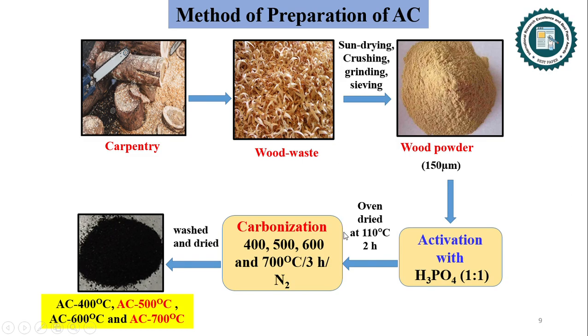The mixture was then heated at 110 degrees centigrade for 2 hours. The resulting sample was divided into four 20-gram portions and carbonized individually at 400 degrees centigrade, 500, 600, and 700 degrees centigrade for 3 hours each under nitrogen flow.